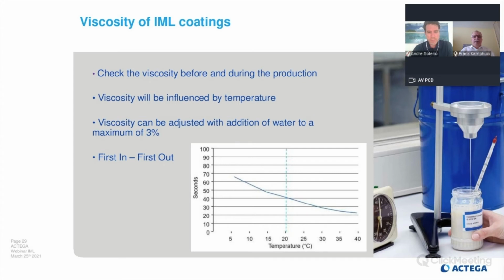Please check the viscosity, that you have the right viscosity. Here we have information for you about the dependency of viscosity on temperature. That means if the temperature decreases, viscosity increases, and if it gets hotter, then the viscosity decreases. Don't worry about that. Measure the viscosity before the production starts, and if viscosity is a little bit too high, you can add water. That's not a problem. And take care of your storage and your goods. So use first in, first out.